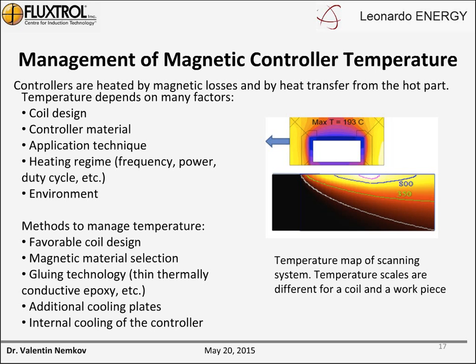Methods to manage temperature. First, it's designing the induction coil favorably. Properly select the magnetic material. Then the gluing technology. For high loading, we recommend a thin, thermally conductive epoxy or similar material. Additional cooling plates could be applied to the magnetic concentrator if required. And in some cases, we can use internal cooling of the concentrator itself. On the right side, you see the maps of temperature inside of the heated part and in the induction coil, that includes copper tubing and the magnetic composite. Pay attention that the scales are different for the part and for the coil.